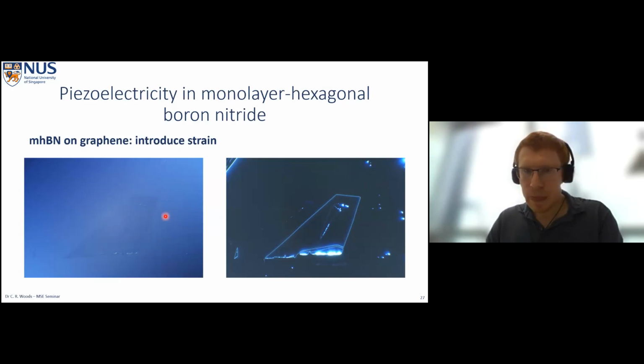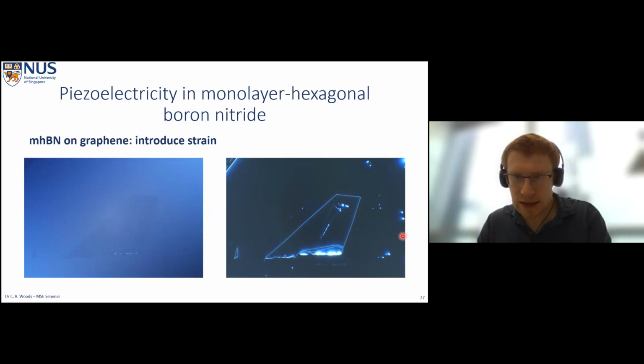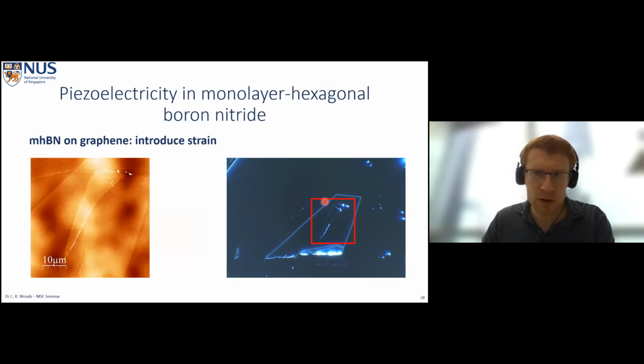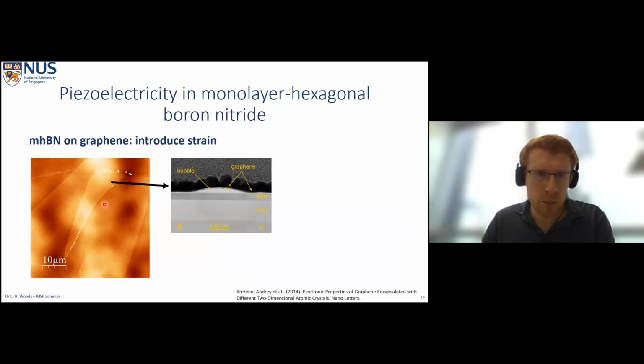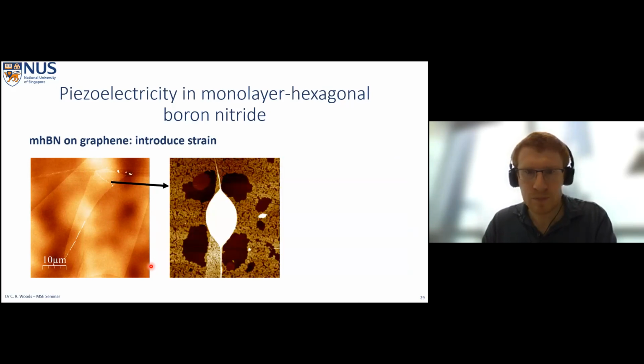Okay, so we produced samples, and they look a little bit like this. I include this just for your information, for your interest. I don't expect you to be able to see the monolayer boron nitride in the very center here, but we have a graphene flake, which is the dark region here, and there's a very hard to see monolayer boron nitride in there. Of course, being a wide-gap insulator, it doesn't have a very strong light interaction, so it's hard for us to see. But if we take the dark field image, you can maybe just about see the scattering from its edges. And we produce samples like this. And when we look in atomic force microscopy, we take a topography image, we have these small bubbles in the region like this, and we can look around them to see if there's some interesting effects. And this is where we see this incidental contamination.